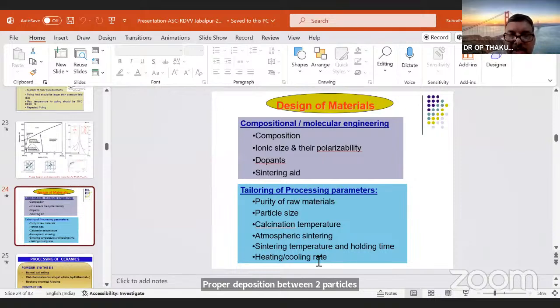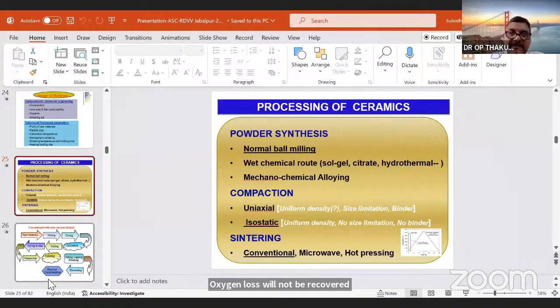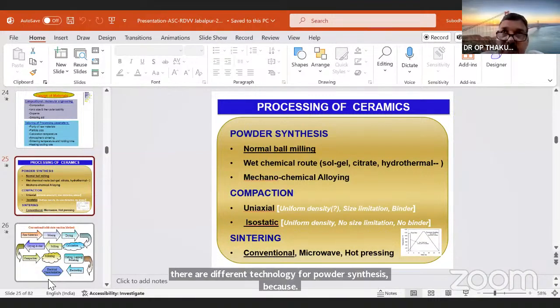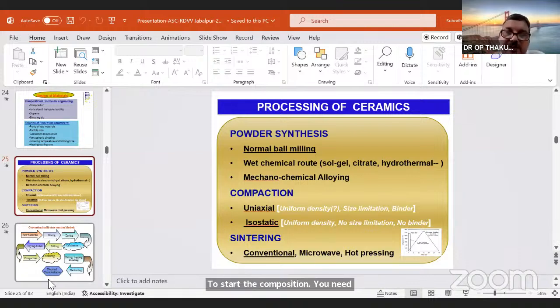The heating and cooling rate is very important, because if you cool the samples rapidly, you will end up with cracks in your materials, or sometimes the oxygen loss will not be recovered. And there are different technologies for powder synthesis, because to start the composition, you need proper control over powder shape, powder size and particle size distribution. Otherwise, each time you will not get reproducible properties. So at every step, you have to check whether your particle size is in the desired range. If not, do further ball milling until you arrive at the desired particle size and particle size distribution. Otherwise, you will not get a similar kind of property at the end.